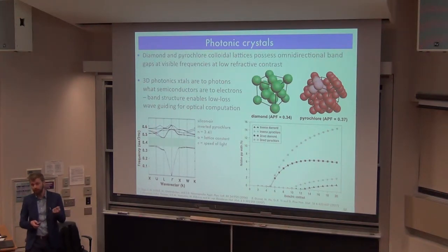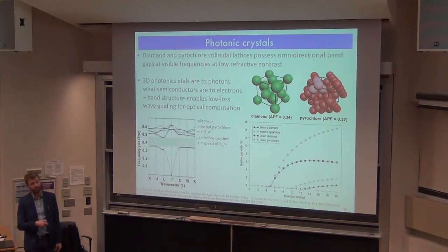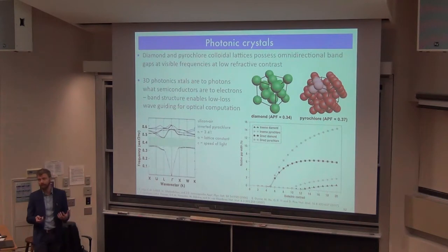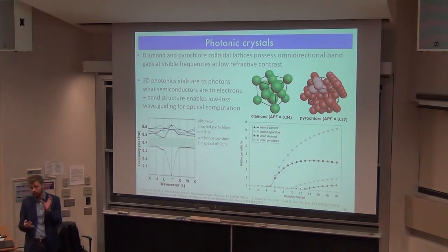The challenge is that 3D photonic crystals require very open architectures with low atomic packing fractions — they don't occur naturally and simple hard or sticky spheres can't produce them. You really need directional interactions to synthesize these. The canonical diamond lattice and its inverse — the pyrochlore lattice, obtained by placing tetrahedra within all gaps of the diamond lattice — are the target structures. The pyrochlore lattice has a band gap at optical frequencies, and only requires a modest refractive index ratio around 3.41, achievable with silicon.